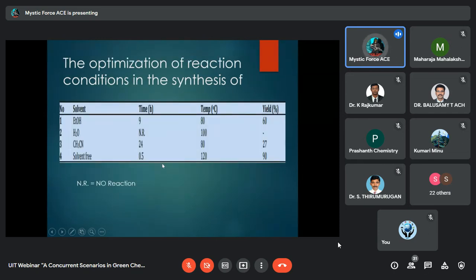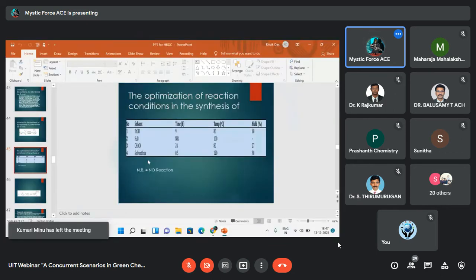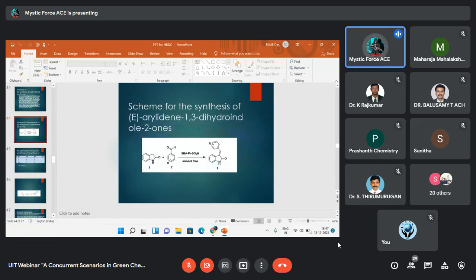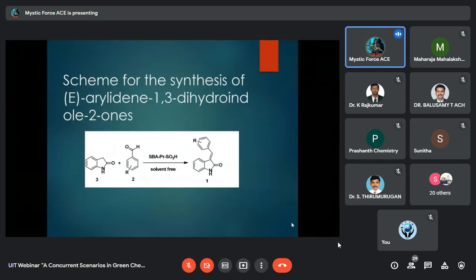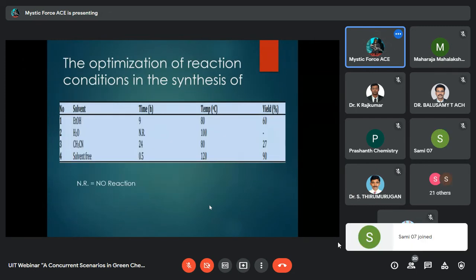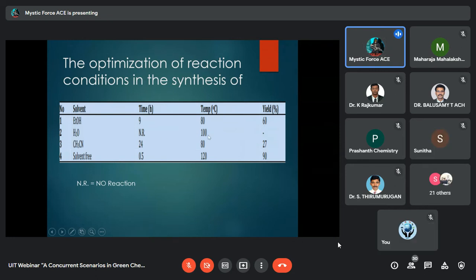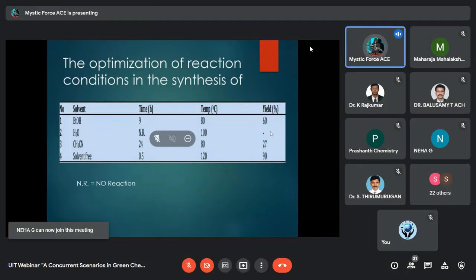Here also the optimized condition of the reaction, which you can see that water, time was very less, temperature was 100, no reaction was there. Sorry. This was the reaction. So when we tried to do it with water, there was no yield. So this reaction was not feasible with water. We increased the temperature also from room temperature to 100 degree, but no yield was there. So what we did, we didn't use any solvent.